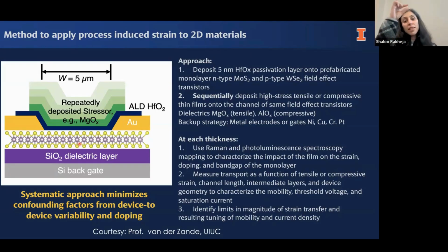They gradually increase the thickness, and for each thickness, they measure the properties of the material. Is the mobility getting better? Is the strain transfer good? Is the current density improving? And then they put more stressor, then they put more stressor. And so for each level of stress, they can measure this property. And this approach is really nice because it gives us very high quality data to calibrate our models to.